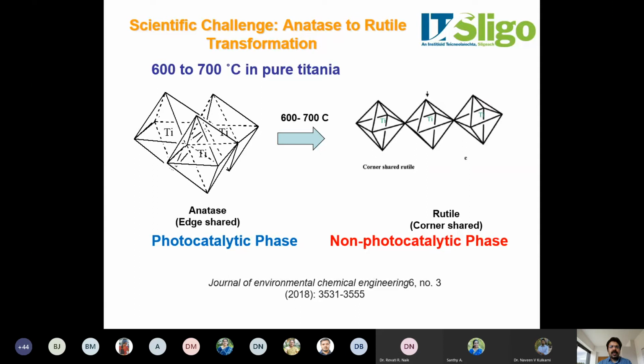So a photocatalytic phase, which is the anatase phase, if you heat it at 600 to 700 degrees Celsius, a non-photocatalytic phase, which is rutile, is formed. So our aim was to prevent or slow this. We don't want a rutile phase forming up to 1000 degrees Celsius, or more than 1000 degrees Celsius, because if you can keep the anatase phase at high temperature, that's what we needed. So we want a high temperature stable anatase phase, which is the photocatalytic phase. So we want to prevent the formation of rutile at the sintering temperature of the ceramic tile.